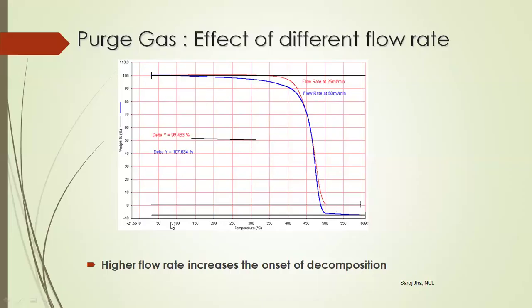This is because the instrument is calibrated at a different flow rate, and you are running your sample at a different flow rate. You will not understand by looking at the scan only what has happened. Why is my sample showing negative weight loss? That is because of the flow rate difference.